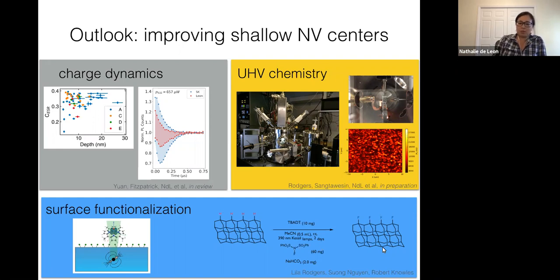And the epicenter for this research is at Princeton. So we started a collaboration with Rob Knowles's group down in chemistry to try to apply this to the diamond surface, and have set up a reaction discovery pipeline involving X-ray spectroscopy and careful surface preparation. And we actually do have some really exciting preliminary hits where we're able to make fluorine terminated diamond with this ambient condition wet chemistry. And we've found that actually this catalysis is very general, and we've been able to make a few other surface terminations as well.